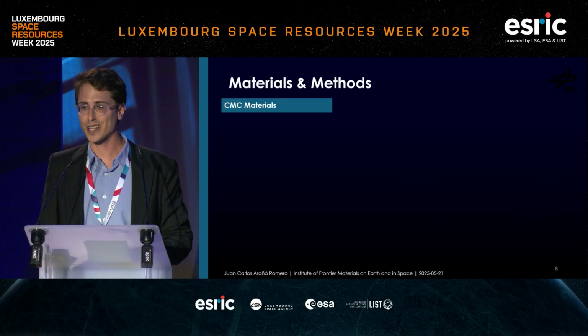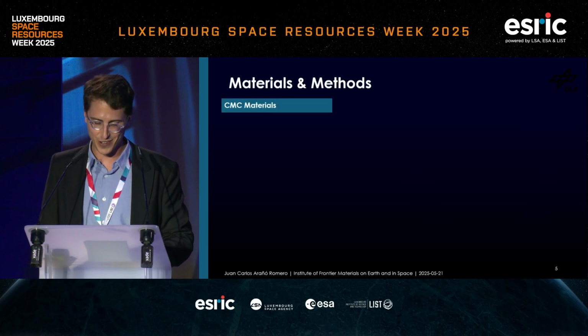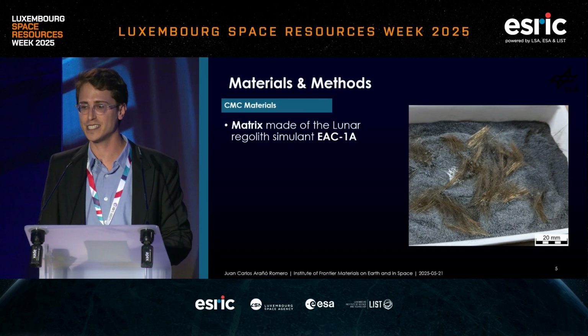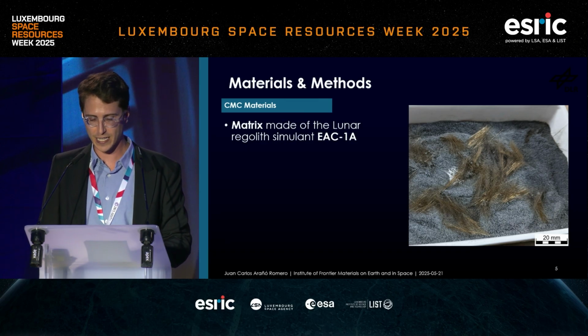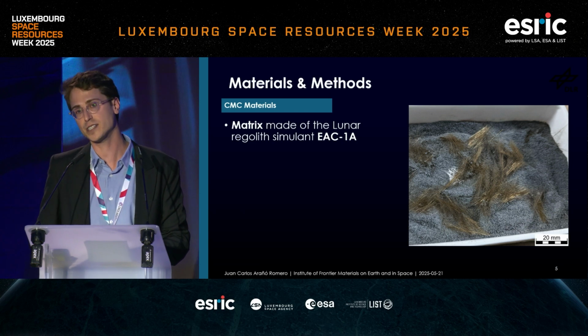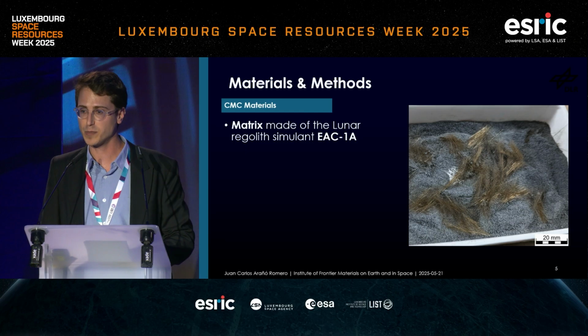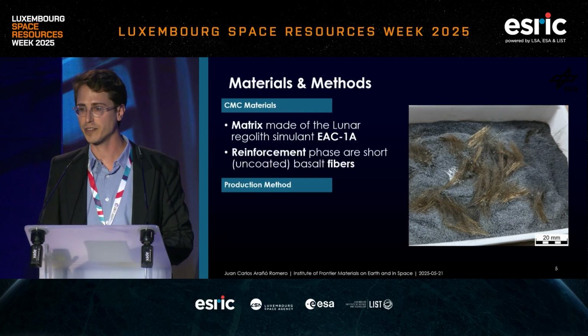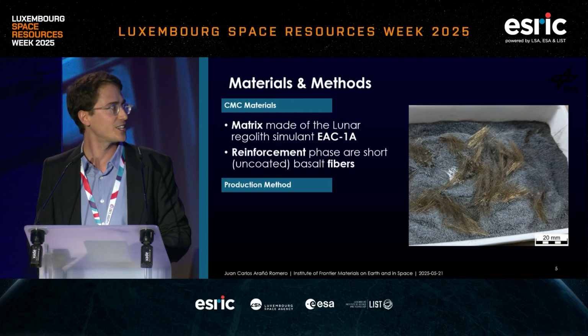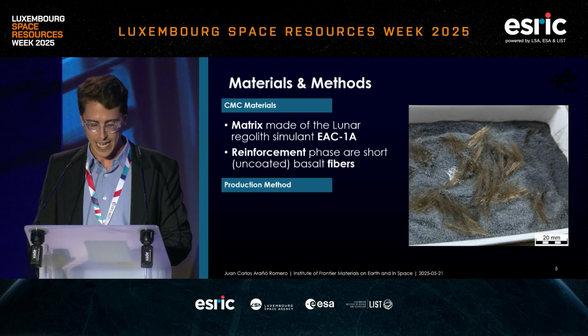So as we already explained, our material is made of lunar regolith simulant, EAC, as well as short basaltic glass fibers that have been made from the same material. And in this picture, you can see in an illustrative way the material that we use. The samples were not exactly prepared like that, but this picture was especially nice because you can see both components. And these fibers were uncoated and have been randomly spread over the layer of lunar regolith.